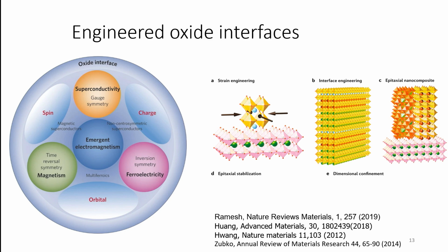So what we do is we take a substrate, some crystal with some well-defined surface structure, and we deposit the material which constitutes the film we'd like to grow on top of that. And if the lattice spacings of the substrate and the film we'd like to grow are not too different, just within a few percent, then the film is going to modify its structure slightly. It's going to stretch itself or compress itself to match the template on which you're growing.